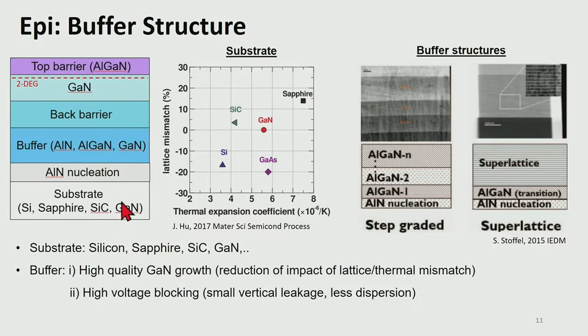There are 2 main roles of these buffer layers. First, it reduces the impact of the mismatch of the lattice constant and the thermal mismatch. And also, it blocks the high voltage in the vertical direction. In terms of the buffer layer design, there are two main types. The first one is a step-graded AlGaN buffer.